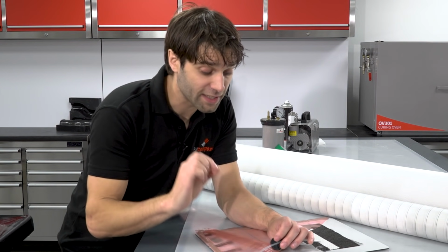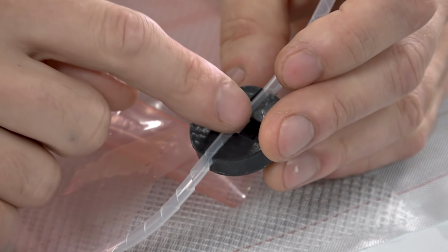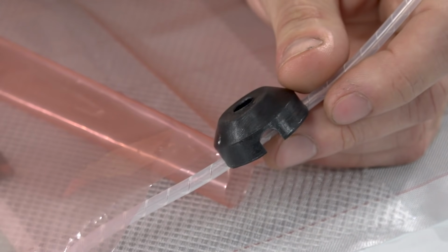To get the resin into the spiral, we have a reusable resin infusion connector. You can't use a conventional through bag connector, for instance, because this will all get surrounded by resin and it would ruin those parts. So these are silicone and they can be torn out from the cured resin.